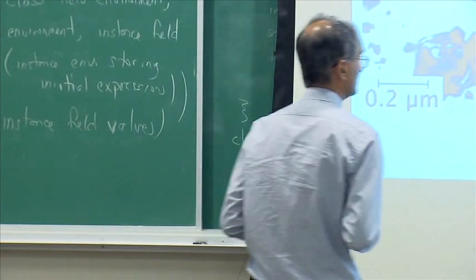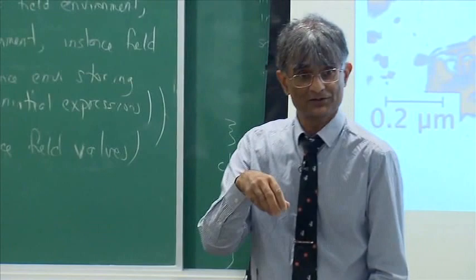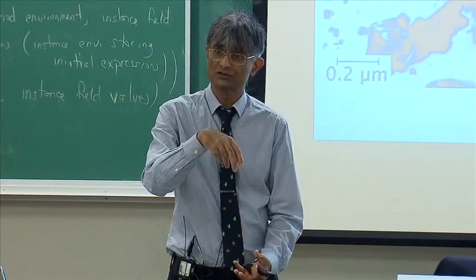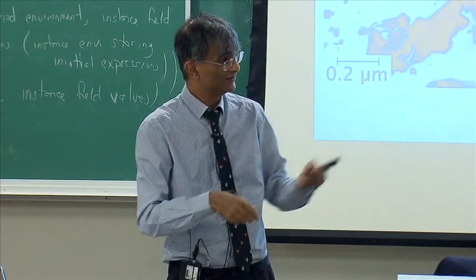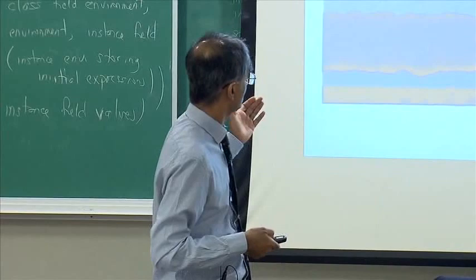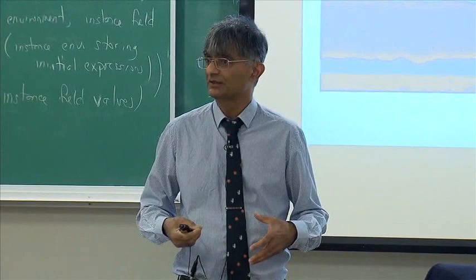If you pass this material through a zone annealing furnace — using an induction coil and pulling the bar through it — you can actually get grains which are meters in length. When we make aircraft engine alloys, we make them as single crystals so there are no boundaries. The alternative is to make a directional microstructure so that grain boundaries are parallel to the stress axis. This can be achieved by introducing potassium into the material, creating bubbles which pin the boundaries directionally. So this long rod has grains going all along its length.